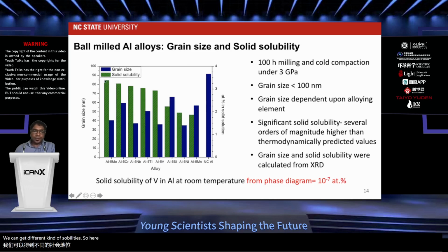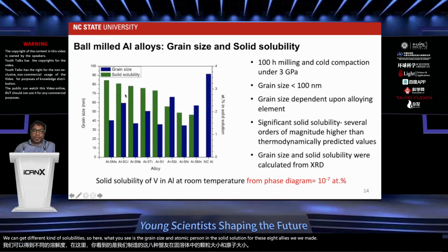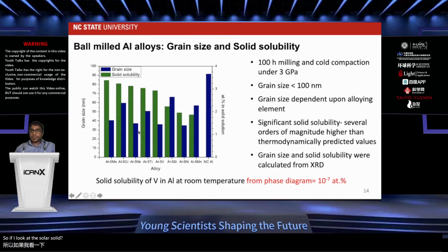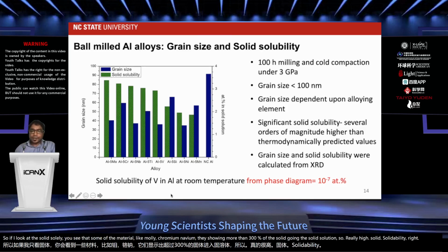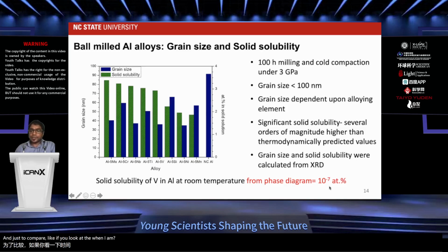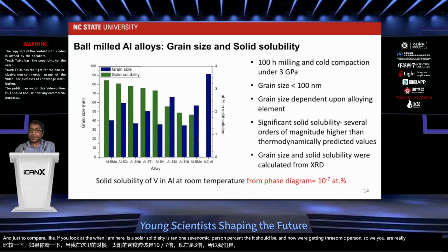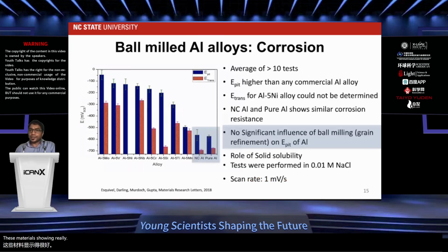So here, what you see is the grain size and atomic percent in the solid solution for these 8 alloys we made. If I look at the solid solubility, you see that some of the materials like molybdenum, chromium, niobium are showing more than 3 atomic percent of the solute going into the solid solution. So really high solid solubility, right? And just to compare, for vanadium the solid solubility is 10 to the power minus 7 atomic percent. That's what it should be. And now we're getting 3 atomic percent. So we are really far from equilibrium. These materials show really high solid solubility, although an inhomogeneous microstructure, right?